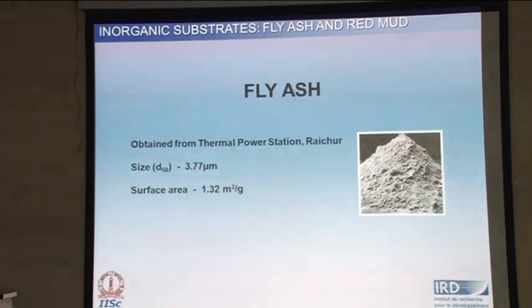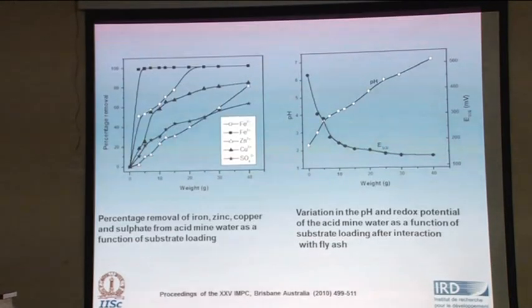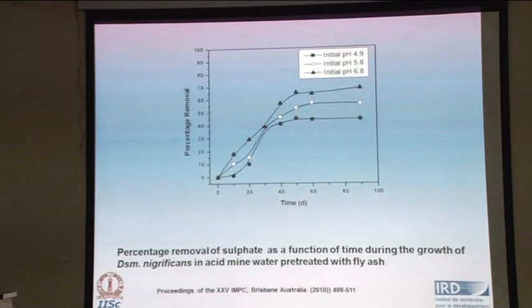So we also looked at some inorganic waste, in this case fly ash. The advantage of the fly ash is that by treating the acid mine water with the fly ash extract, you can actually increase the pH, which is going to be more effective when you use the sulfate reducing bacteria. And correspondingly, the redox potential also decreases. You will see complete removal of iron, as we saw in the case of the organic substrates, and then sulfate reduction is to the extent of about 50%. This can be further improved when you add the sulfate reducing bacteria, Desulfomicrobium nigrificans. Again, you see that about 60% sulfate could be reduced as a function of pH.